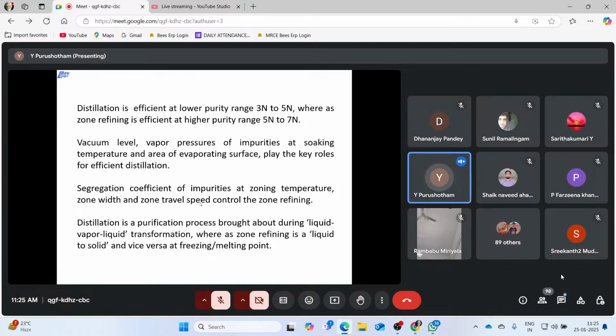These are the process parameters: vacuum level, vapor pressures of impurities at soaking temperature, and area of evaporating surface play the key roles for efficient distillation. And segregation coefficient of impurities at zoning temperature, zone width, and zone travel speed control the zone refining. These are the experimental parameters one can work on if anyone wants to do any metal purification or develop a new technology. Distillation is a purification process brought about during liquid-vapor-liquid transformation, whereas zone refining is liquid to solid and vice versa, at freezing or melting point.